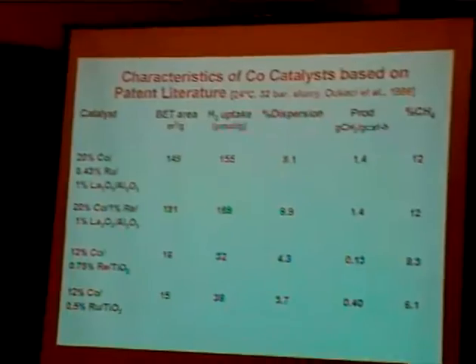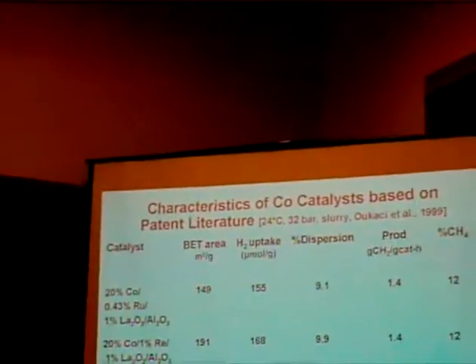Now that's what you'd like to have. In a very interesting study by Oukaci et al., they actually prepared different catalysts based on the various patents, then compared their properties—BET area, hydrogen uptake, dispersion—and their productivities. What you see is that catalysts with high BET areas, high chemisorption uptake, and relatively high dispersions around 9 to 10% have productivities indeed in the range you'd like for a commercial catalyst, whereas if you don't have those properties, you get much lower productivities.